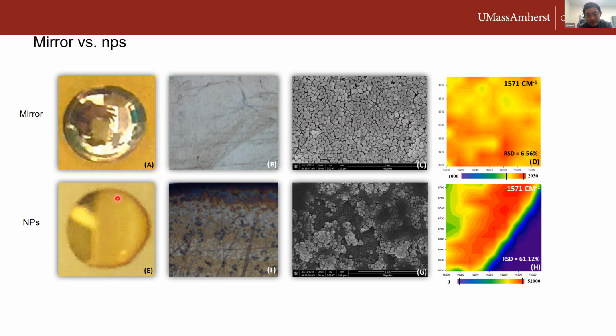Another advantage of this silver mirror is that it can be applied on many surfaces, like polymers, metals, or even plant materials. In this case, we drop the mirror on a spinach leaf to detect pesticide residues. As we can see here, when dropped on the spinach leaf, it covered the spinach pretty well. It still forms a very uniform mirror coating. If we look at the right-hand side, here is the signal recovery. We can successfully detect the pesticide down to 1 ppm using the mirror method. In this case, it's the gold mirror. My bad, I was talking about the silver mirror.